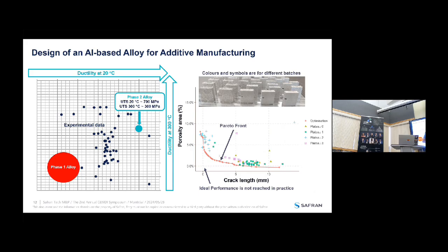So you see that the triangle and the square, they're actually the first specimens, the first set of parameters inferred by material experts and AM experts. And so we used these data to build a model of crack length and porosity area as a function of parameters and try to optimize both of them to reach the ideal point of 0, 0. So you can see that we started from something that was fine in terms of porosity, but not fine in terms of crack length.